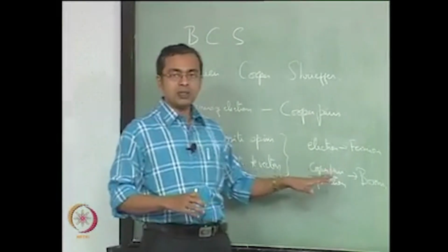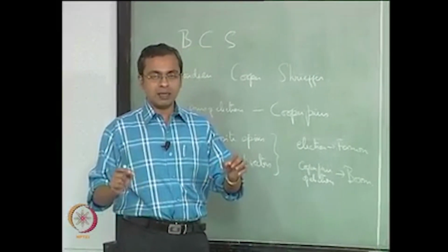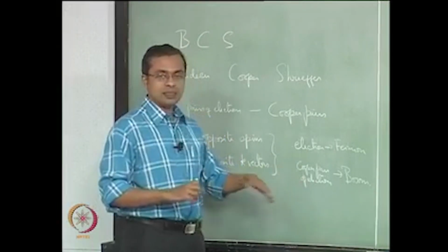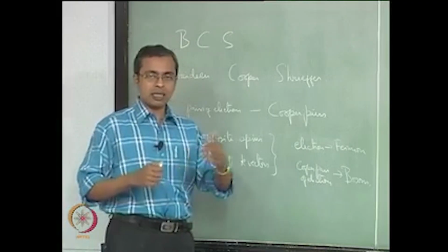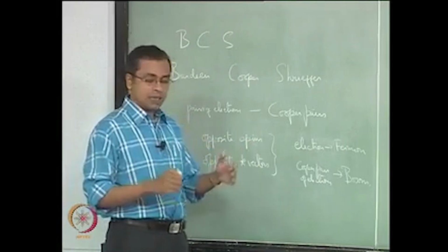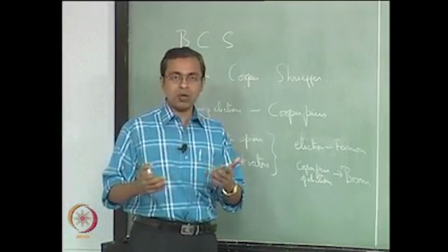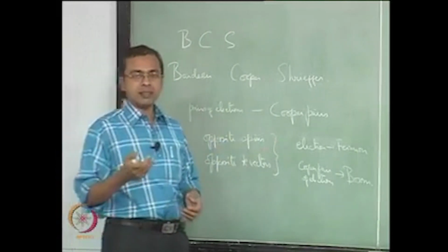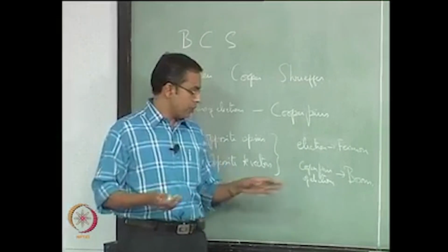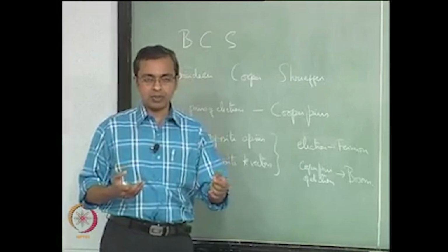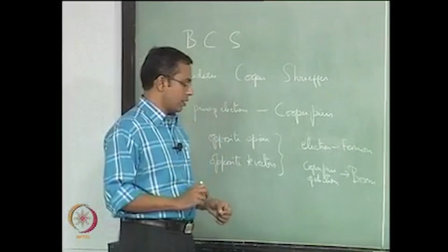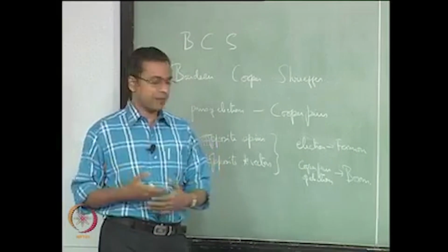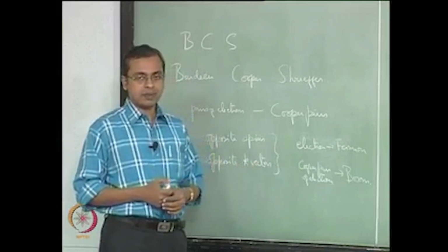Okay, so they sort of condense into this state wherein they are in this paired state, and because they are paired with each other, in this condensed state they avoid the interactions with the lattice, or they are somewhat impervious to the scattering events that normally electrons are prone to. They tend to be relatively far apart. Atomic distances are of the order of angstroms, but these electrons could be of the order of several nanometers apart, and they would still continue in a coordinated way. Therefore, within a certain length scale you may have several Cooper pairs confined to the same length scale.